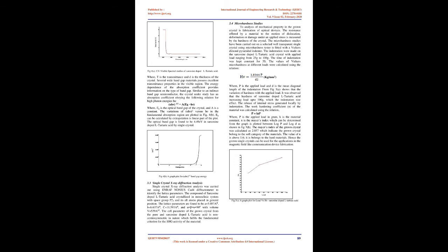The variations of (αhν)² versus hν in the fundamental absorption region are plotted in Fig 4b. Eg can be calculated by extrapolating the linear part of the plot. The optical band gap is found to be 4.49 eV in the sarcosine-doped L-tartaric acid single crystal.